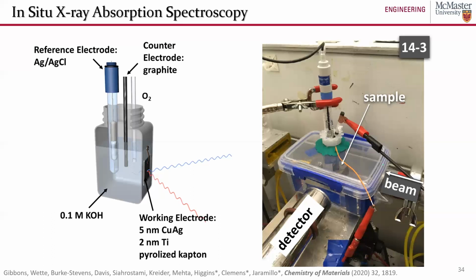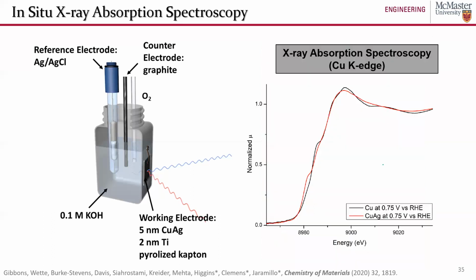We set these materials up in front of our synchrotron X-ray beam, and we collected X-ray absorption spectroscopy at the copper K edge. Now I don't want to dive into the weeds of this particular technique, but really we wanted to characterize what the oxidation state and what the structure was of these materials under operating conditions, or under electrochemical potentials, where that reference electrode was really important for making sure that we had reliable electrochemical potentials, because we were comparing the results from one experiment to another.